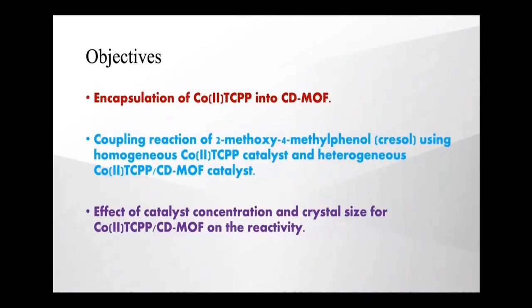In this research, we encapsulated cobalt TCPP catalyst into CDMOF during the crystallization by vapor diffusion of methanol. We carried out the coupling reaction of cresol by using the heterogeneous cobalt TCPP CDMOF catalyst. We investigated the effect of catalyst concentration and crystal size for cobalt TCPP CDMOF on the reactivity.